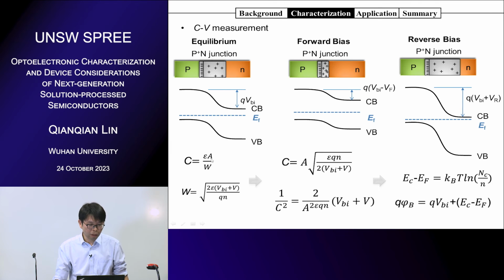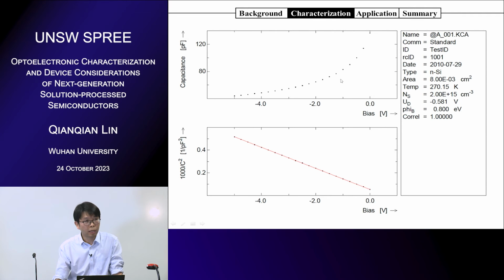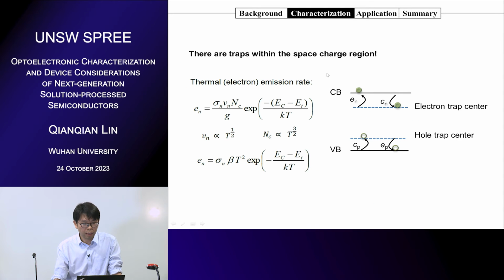Then we combine these two equations, and you can get the bias-dependent capacitance. If you rearrange this equation a little bit, you get the reciprocal of C squared, and this number is linearly dependent on voltage, right? From this measurement, we normally plot it like this, and from the steady-state CV, we can get the carrier density and also the built-in field. This is a typical measurement from the equipment. We can get the steady-state CV, which has nothing to do with traps.